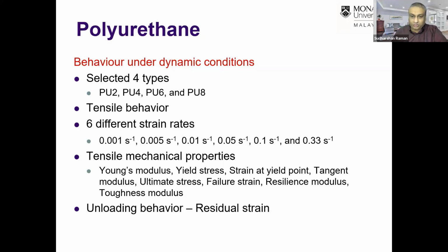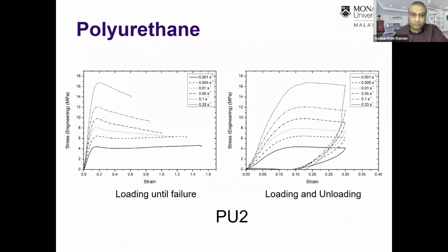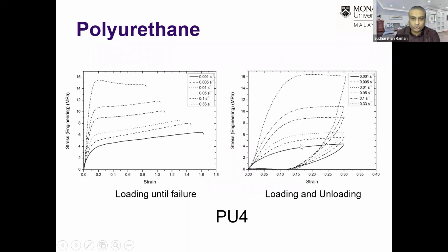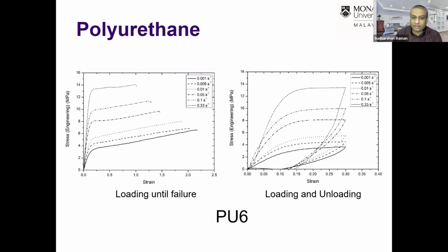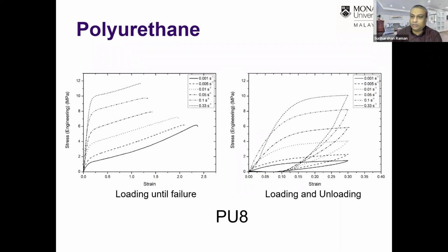Okay, so this is for PU2. As you can see, when the strain rate was increased, the elongation capacity reduces, whereas the graph on the right shows the loading and unloading behavior. Okay, this is for PU2, PU4, PU6, and then lastly PU8.